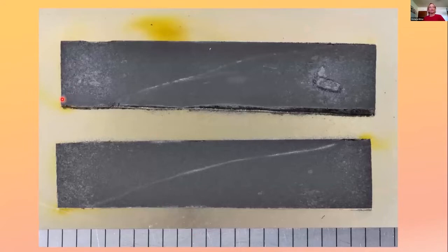This is magnified. This is a 1/2 inch tall, cut long ways, and you can see the weld started from here, went to here, and you can even see where it got a little crumbly there, where it might have got a little too hot. This was a fluxless weld, so this had to be heated to a little higher temperature and cause those little cracks. But this line is not drawn in there. That is exactly how this metal looks.